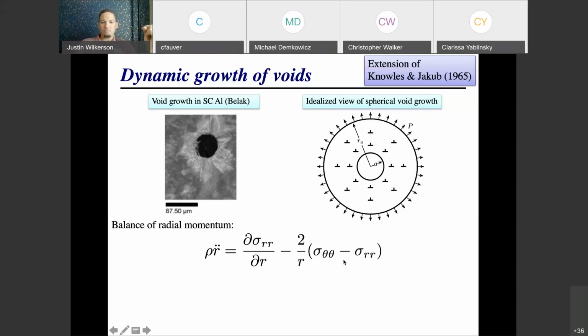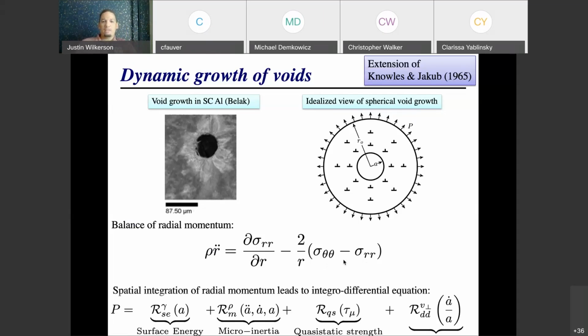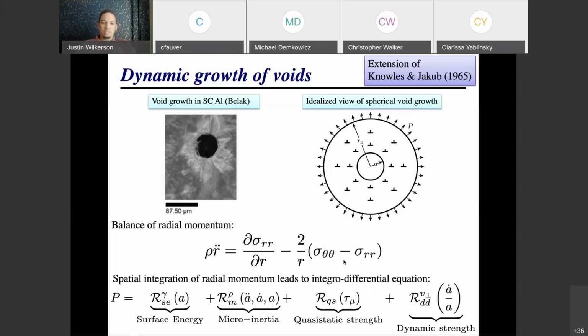And so sigma theta theta minus sigma r for a spherically symmetric problem is just the von Mises stress, or the deviatoric stress. Okay. And if I take that balance of radial momentum equation and integrate through the thickness of the spherical shell, starting at r equals a and integrating from this surface out to the outer surface, and then apply my boundary conditions. So when I integrate this derivative of the radial stress with respect to r, that's the integral of a derivative, so it's just going to be the radial stress itself, which then becomes the boundary conditions: the applied pressure at the outer surface, and if there's any Laplace pressure due to surface tension at the inner radius of the void.